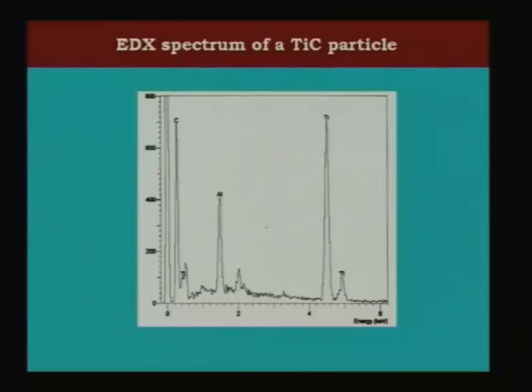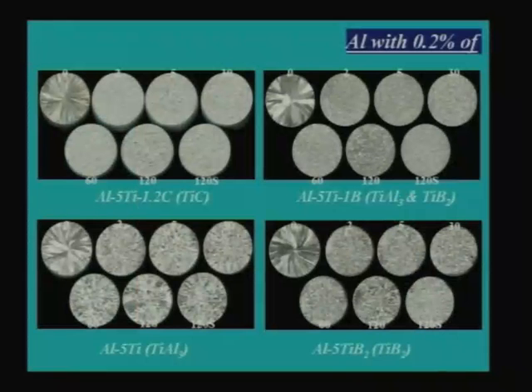That means you take a known weight of aluminum titanium carbide composite, and that known weight you try to dissolve into, let us say, a sodium hydroxide solution and take out all the particles that come out and weigh those particles. From that one can get an idea of what is the weight fraction of those particles. Okay. And look at those particles in the EDAX also, confirm that there are only TiC particles, and here I am not showing you the mechanical properties which are similar to that of the TiB2, but looking at the grain refinement behavior of this. Look at this alloy which is added to pure aluminum, okay,